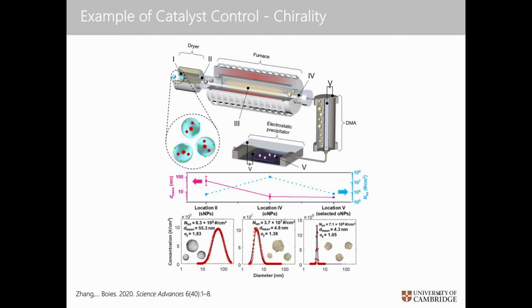The other way we could do it is we could simply size select catalysts. So all these techniques that I told you about how one measures particles, those can be used as size selectors for reactors as well. So you can put a particle in an electric field and only let a certain fraction of those through, and those could have extremely narrow size distributions. And I mean narrow at the angstrom level, so 4.3 nanometers exactly. And you can bring that into a reactor, and that is very useful. It allows you to grow fantastic nanotubes.